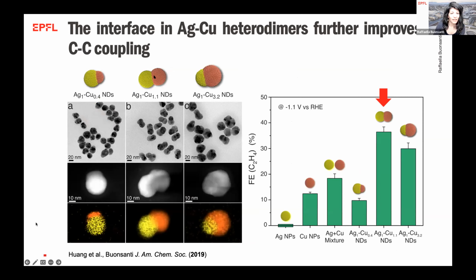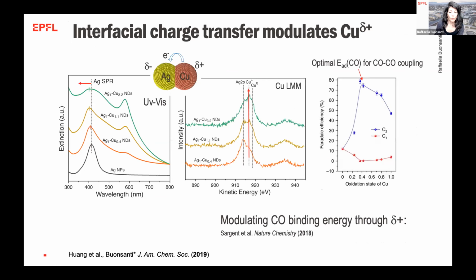However, then we also started to create what we refer to as heterodimers, where copper and silver share an actual interface, so they're epitaxially grown into each other. And what we found is that this interface between the two domains further enhances the C-C coupling capabilities. What we demonstrated by combining UV-vis and XPS measurements is that a charge transfer occurs between the copper and the silver, which leaves behind a slightly positively charged copper, which can modulate the CO binding energy.